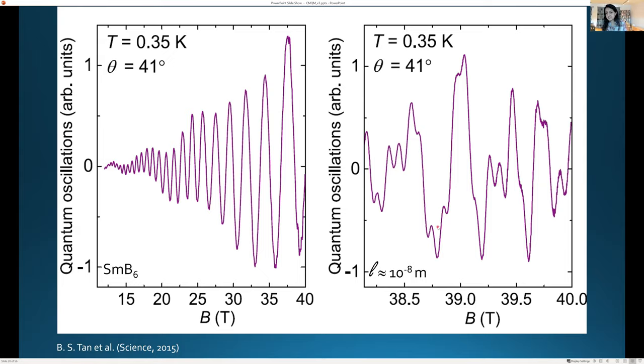So what this means is that it appears as though the electron is executing cyclotron orbits, which require mean free paths of about 10 to the minus 8 meters. So I told you before that the resistivity is so big that the mean free path would only be about 10 to the minus 15. So something has gone wrong in our understanding. There's about a million times difference between what quantum oscillations imply the electrons are traveling in terms of cyclotron orbits and mean free paths, and what the electrical resistivity seems to show, in terms of electrons are stuck in one place. I'll come to what this might mean, but right now, this is just an empirical observation.